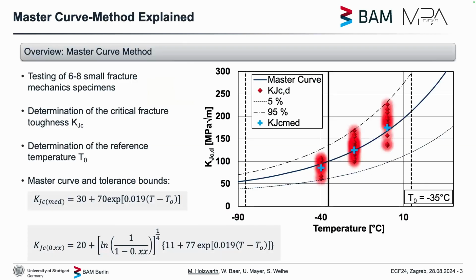This is now, thanks to the previous talk, a quick repetition to refresh the mind. What's the master curve? Basically, we have to do a very small amount of tests. And with this small amount of tests, we can then do an evaluation of the reference temperature T0. And with this reference temperature, we get then this graph here. And the reference temperature T0 is here, the big bold line in the middle.